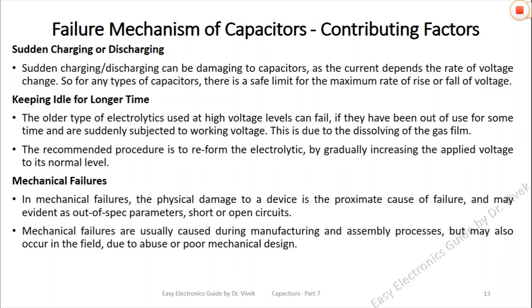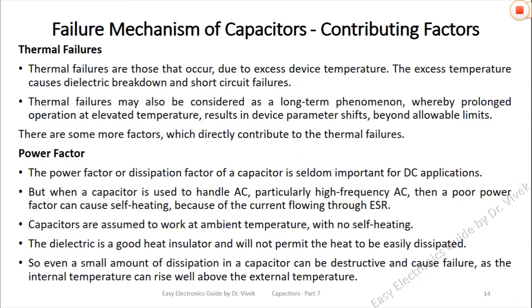Sudden charging or discharging can be damaging to capacitors as the current depends on the rate of voltage change. Keeping idle for a longer time and suddenly being subjected to working voltage can result in capacitor failure, especially in electrolytic types, due to the dissolving of the oxide layer. In mechanical failures, the physical damage to a device is the proximate cause of failure. Thermal failures are those that occur due to excess device temperature, which causes dielectric breakdown and short circuit.